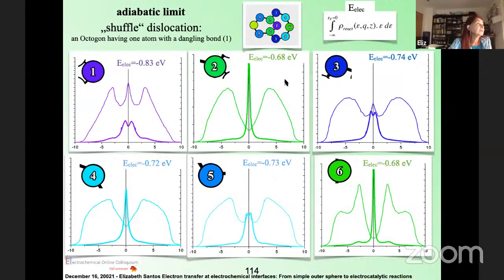Here the density of states at the Fermi level is very, very low, and then the reactant does not have such a strong interaction. But when states appear in the gap, in the mid gap, near the Fermi level, and the reactant comes into the region where the Fermi level is, we see that it could produce a strong interaction.